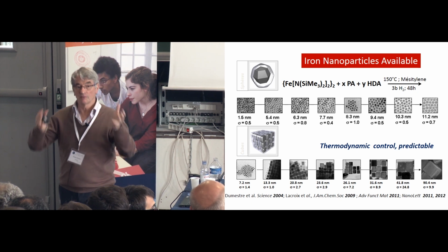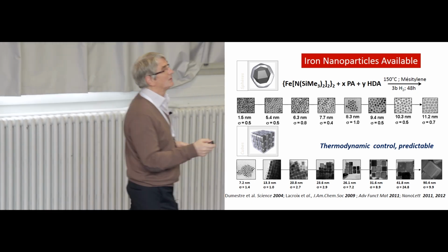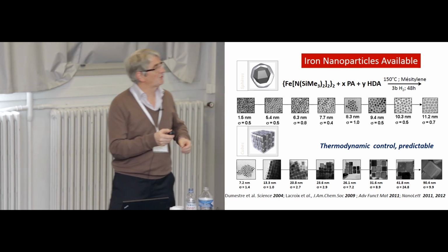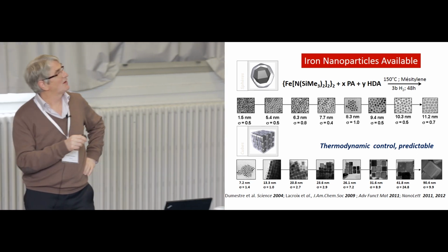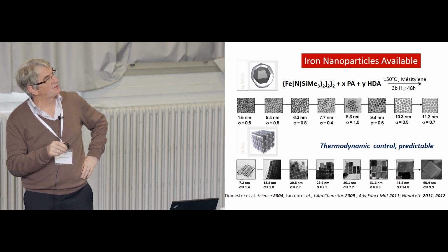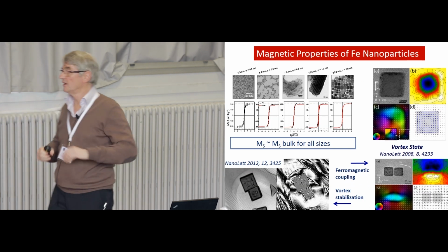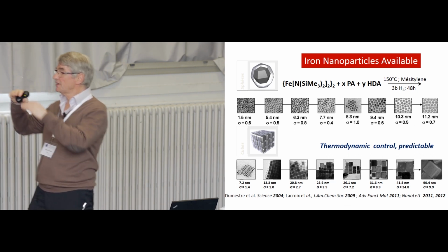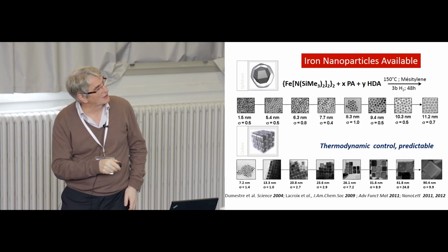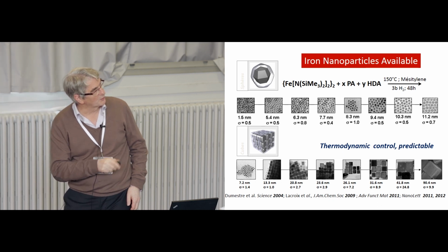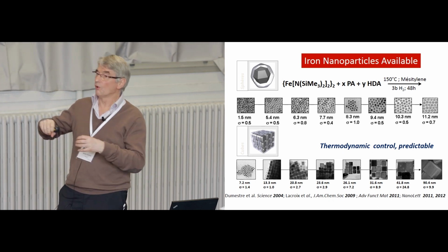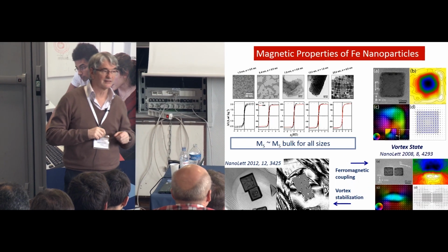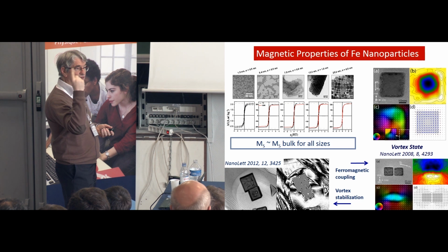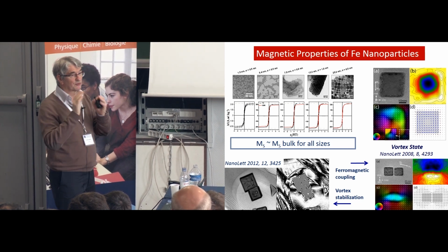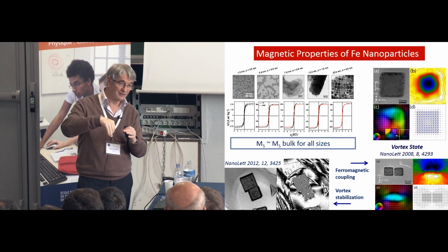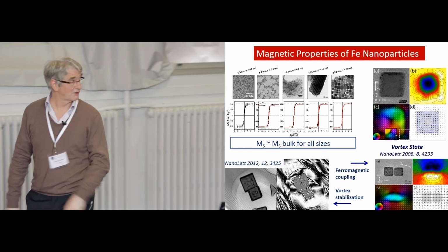Playing on X and Y, we could make a series of dispersed spheres and cubes. They have good magnetic properties. Some have funny properties, like this vortex state, which is between monodomain and polydomain. The vortex state can be quenched by ferromagnetic coupling, or if you put holes in the cube, you can stabilize the vortex. The interest of vortices is they can turn right or left, so in principle you have 4 ways of storing information over a vortex, but that's another story.